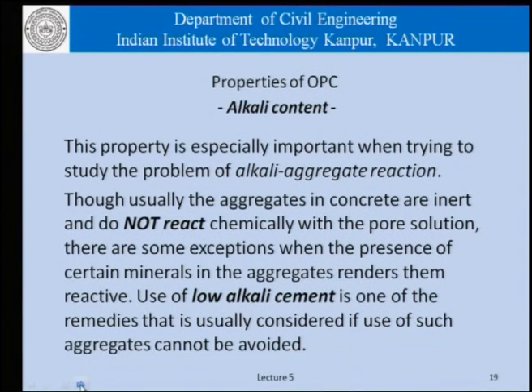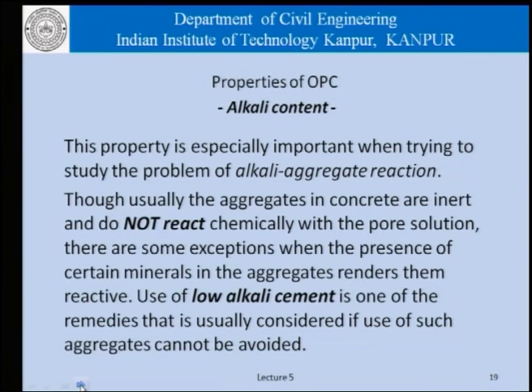The alkali content is especially important when studying the problem of alkali aggregate reaction. Though usually the aggregates in concrete are inert and do not react chemically with the pore solution, there are some exceptions — the presence of certain minerals in the aggregates renders them reactive. They react with the pore solution which may have sodium and potassium ions and hydroxyl ions, and this reaction leads to premature deterioration of concrete. In such cases, when the aggregate is reactive, the use of low alkali cements is one of the remedies that can be considered when the use of such aggregates cannot be avoided.